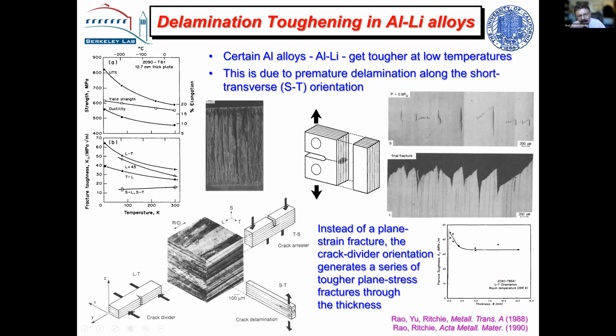If we propagate the crack down those layers, the layers are quite weak and you get a very low toughness. But conversely, if we propagated a crack in this orientation where the crack is growing perpendicular to those weak layers, you get what's called the crack arrestor orientation. That's like breaking wood against the grain. That's a very tough situation. Now, those two are pretty obvious, of course, but the one that's not so obvious is the other orientation where the weak planes divide the crack. And this is known as the crack divider orientation.